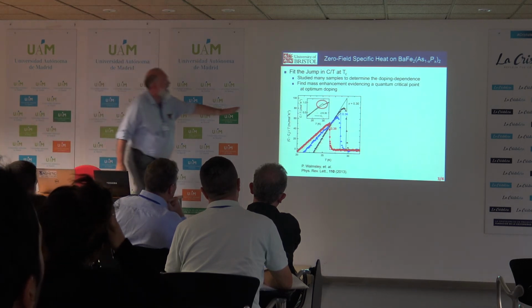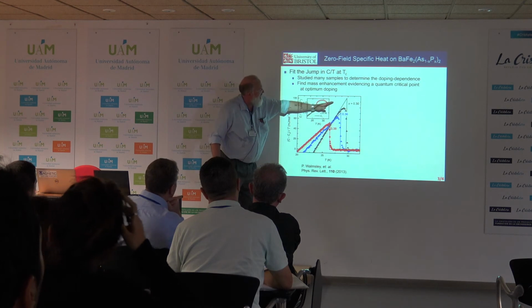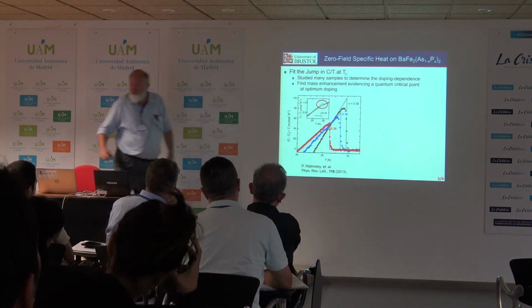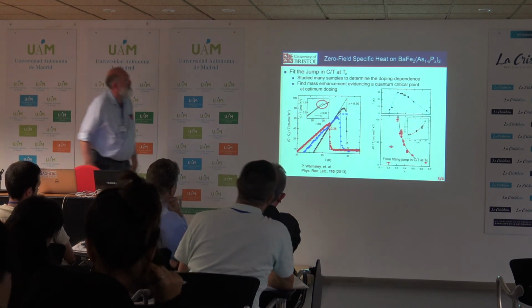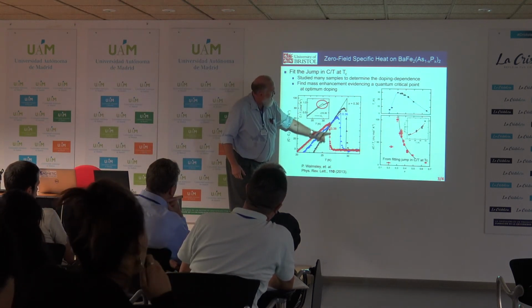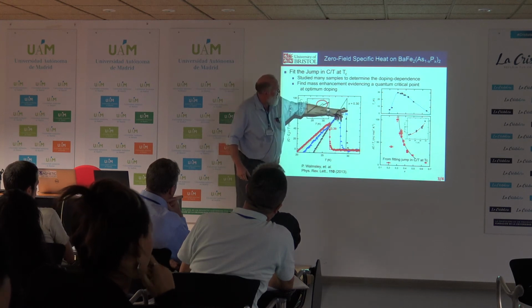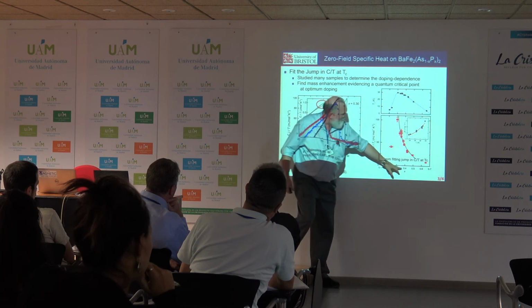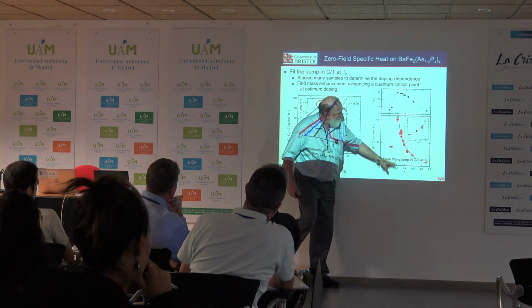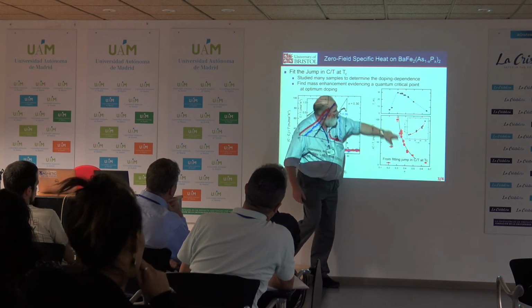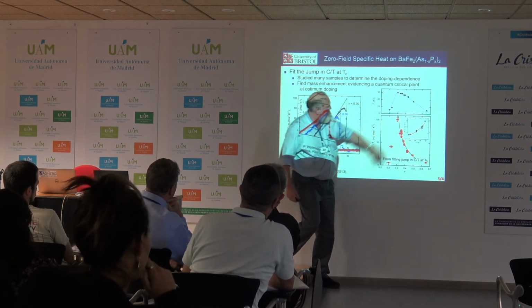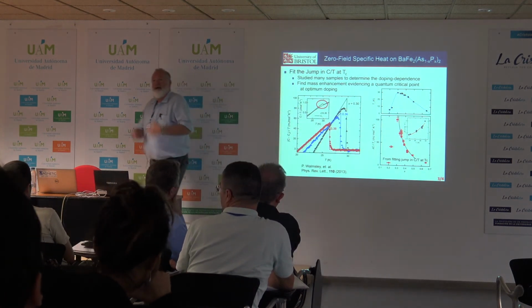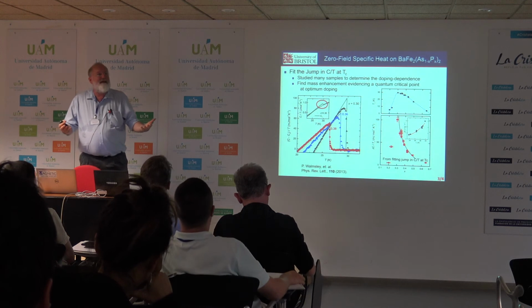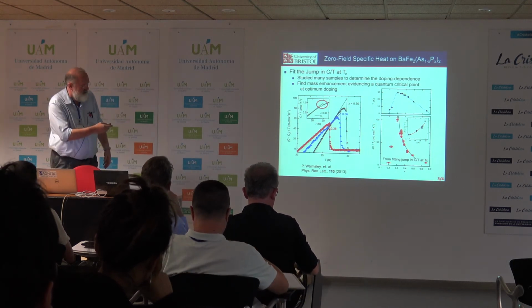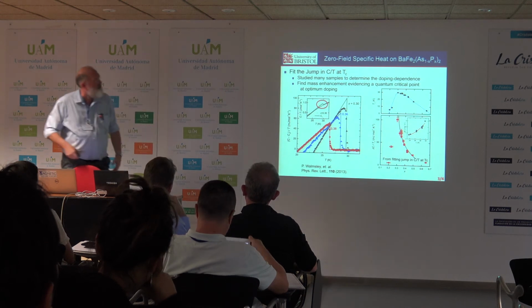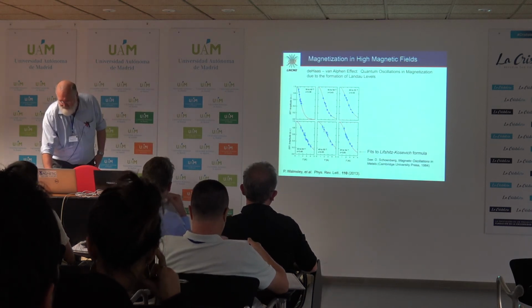And so they're measuring on the back of this phonon background this jump at TC, and they remove this normal state specific heat in order to do this analysis. And what they find is a dramatic increase, as you can see, going from 0.38 phosphorus doping to 0.30. This jump is almost doubling. Here from 0.38 to 0.30. 30 is the optimum TC. You see this huge enhancement in the jump at TC. And that's evidence of a mass enhancement. But it's a little bit harder to analyze. It's a many band system. But clearly there's a divergence. They fit it to a logarithmic divergence, as you would expect from a magnetic phase transition.